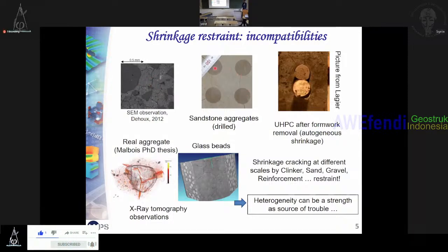So you can observe it also here, and also by X-ray tomography. So here you have an aggregate and cracking, but also, of course, rebar is very good. Fibers are very good for concrete, but you have no shrinkage in rebar or in fibers. So you have a restraint also of drying shrinkage, autogenous shrinkage, of concrete by the rebar, which may give rise to tensile stress and even in some cases to cracking inside the concrete. So heterogeneity also can be a strength, but also a source of trouble. So it was also the case of drying.